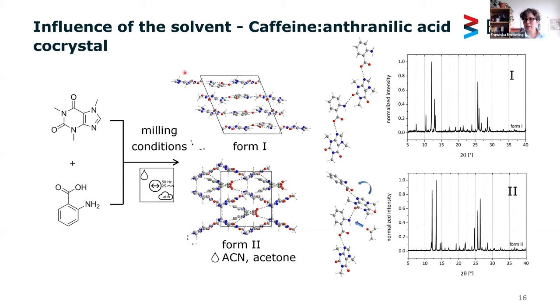Here again, it's a co-crystallization, caffeine and anthranilic acid. It's a system that has been studied by many colleagues, and we have two forms. And we also know two polymorphic forms. And we know that the outcome of a mechanochemical reaction can be targeted specifically if we use specific solvents. Usually we end up with this thermodynamically stable form one with all the solvents, but if you use acetonitrile or acetone, we get this other form.